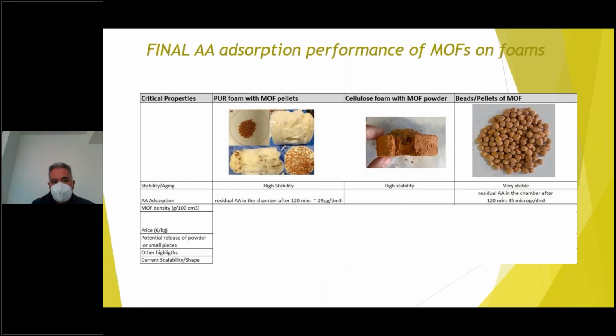Finally, we have different supporting structures for the MOF sorbents. We developed polyurethane foams with MOF pellets. We have cellulose foams with MOF powders, as I have explained. And if we compare with the typical shaping process that was explained by my colleagues Katia and Maria, we have the pellets. The three supporting structures offer very interesting properties from the acetic acid adsorption point of view. We are talking about residual acetic acid in the chamber after 2 hours of around 20, 30 ppb, which is suitable for the application that we're talking about.